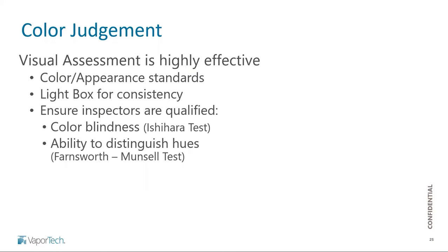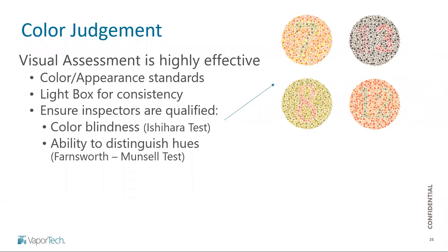And then another thing is you really want to make sure, if people are doing this visually, that your inspectors are qualified. A big issue is color blindness. 1 out of every 12 men have some degree of color blindness, 1 out of every 200 for women. One of the ways in which this is evaluated is this Ishihara test, which you've probably seen before, a collection of colored dots, and you're looking to see if you can distinguish the number within. There's standardized books on this, but I found there's also free apps for your phone that you could just download and do a quick test. It's probably not the best official test, but if you want to get an idea of whether or not you've got a deficiency or your inspectors have a deficiency, it's probably a good first pass.